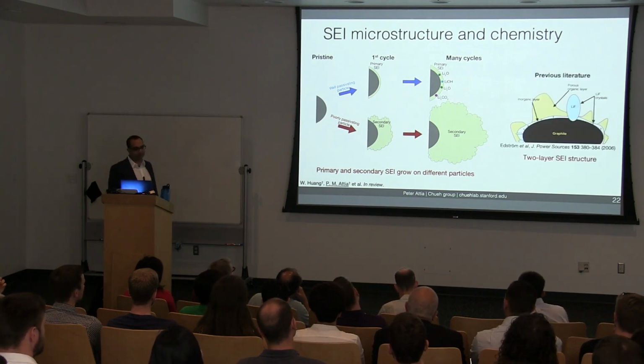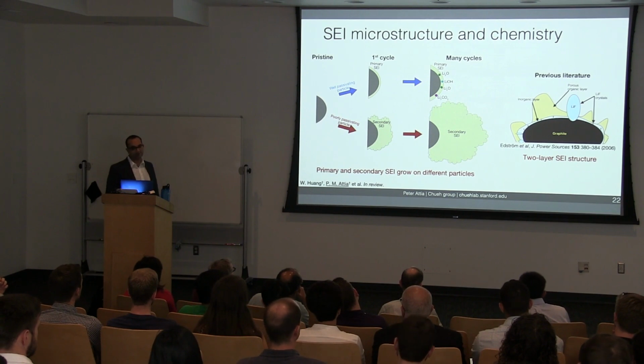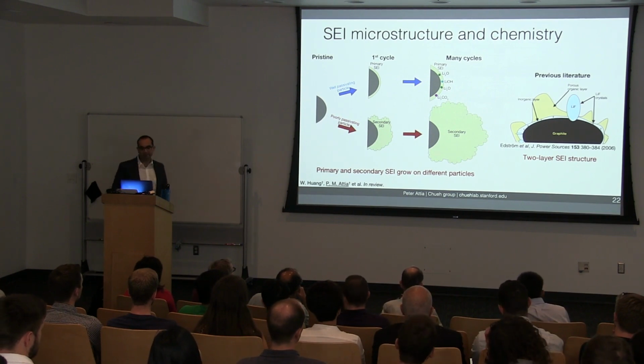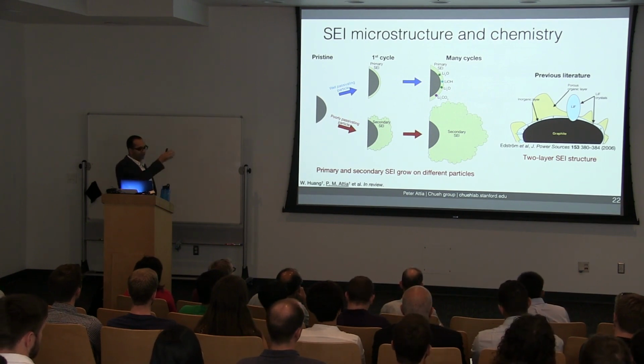Another thing to note is that we have a slightly different finding than previous work. Most previous work talks about a two-layer structure of SEI with a thick organic layer above a thin inorganic layer. What we find is that both of these motifs exist, but they exist on separate particles. So it seems to suggest that the two-layer model is wrong. And the fact that we're able to directly determine this really speaks to the power of Cryo-EM.